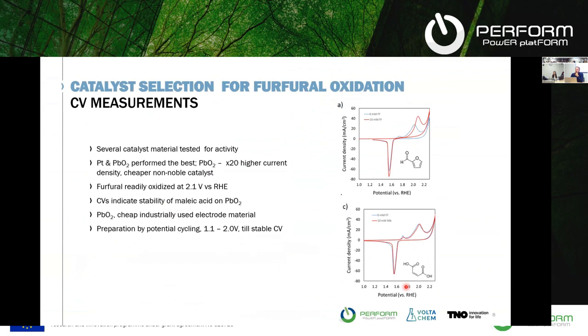So initially, you typically start with catalyst selection, and I will focus more on the furfural to maleic acid side, but the same reasoning can be applied to the levulinic to valeric acid. So initially, we need to find an electrocatalyst that can carry out the electrochemical reaction that we want. And we tested quite a lot of different materials, different transition metals, precious metals or not.